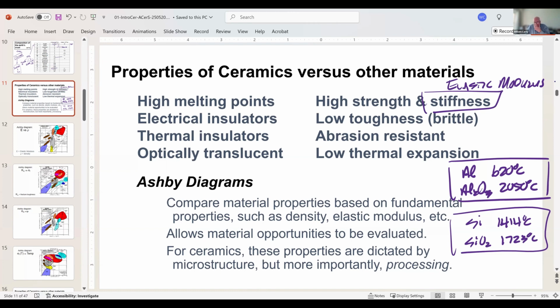They tend to be brittle. So we're going to spend a lot of time talking about brittle behavior, but essentially brittle behavior is that once a crack starts to propagate in that material, there's nothing to stop it. So the crack will speed through the material. Typically the velocity of the crack is the speed of sound in the material. And so there are no intrinsic atomic bonding type mechanisms or microstructural mechanisms, for the most part, in these materials that can absorb that crack energy and slow that crack down.